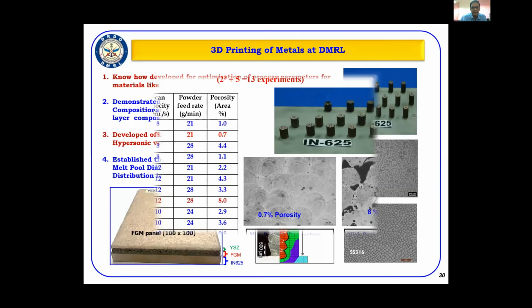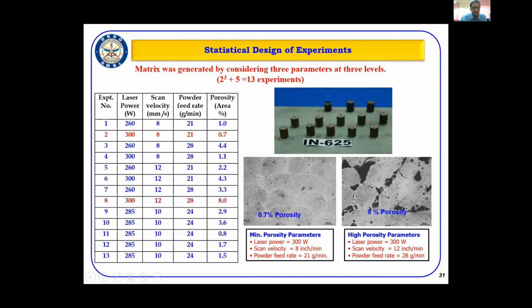If you see the matrix, this is the matrix we have generated for 13 different specimens to obtain the optimized parameters. I would like to have your attention on experiment number 2, where the laser power is 300, scan velocity 8, and powder feed rate 21. We obtained a porosity of about 0.7%. Whereas for the same laser power, with a different scan velocity and powder feed rate, the porosity was 8%. That means it was only 92% dense. So such things are possible, and one has to obtain the optimized parameters before going in for the actual deposition of the component.